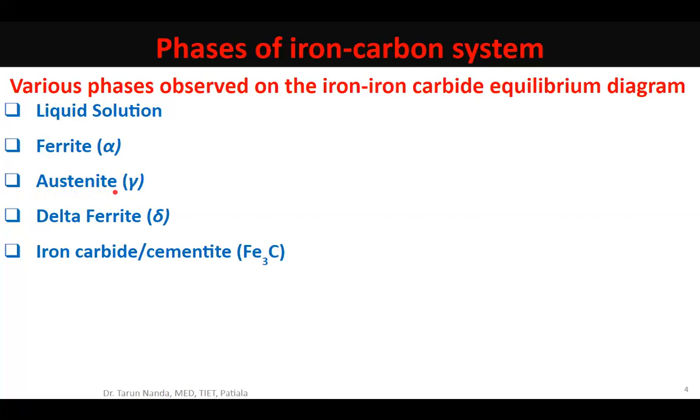But that's a costly affair because the alloying elements like nickel are costly. In materials like austenitic stainless steels, a 100% austenitic microstructure can be seen even under room temperature conditions. But under normal conditions, austenite is a high temperature phase. It would be an equilibrium, stable phase only under high temperature conditions in excess of 910 degrees centigrade.